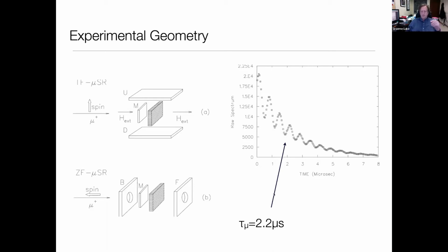Of course, we know the muon lifetime very well. It's 2.2 microseconds, so we can divide that out, or what we normally do is we take opposing sets of counters, because of course if the spin is pointing towards this particular counter when it decays, it'll be pointing away from that one. So the signals will be exactly 180 degrees out of phase. And then we can take what we call an asymmetry, which is just plotting the difference in the count rates divided by their sum, and the muon lifetime disappears, and we just measure the spin polarization function.